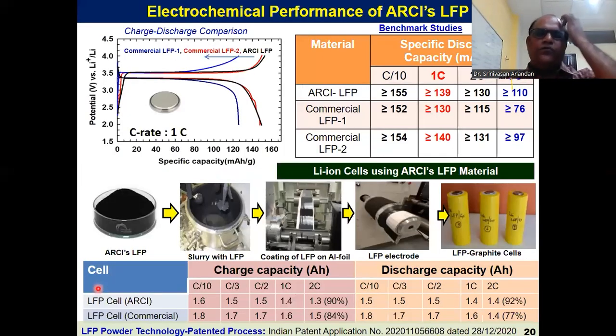And here I would like to show the performance of ARCI LFP material at the point cell level as well as in actual lithium-ion cells. This shows the typical charge discharge profile of LiFePO4, and you can see the capacity of ARCI LFP material at 1C. 1C means you are giving 1 hour for charging, 1 hour for discharging. At this current rating, the capacity of ARCI LFP material is about 139 milliampere hour per gram, which is close to the commercial material.